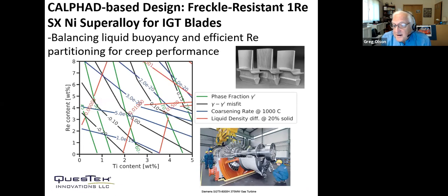That's had an important impact on the actual design with uncertainty practices that we've then established. It was actually in the late 90s that Howmet called to our attention the problem of trying to scale up single crystal turbine blade alloys from the aeroturbine scale to the very large scale of industrial gas turbines. And the problem here is the macro segregation defects, so-called freckles, that are driven by thermosolute convection. The physics of the problem was already well established in the late 90s.